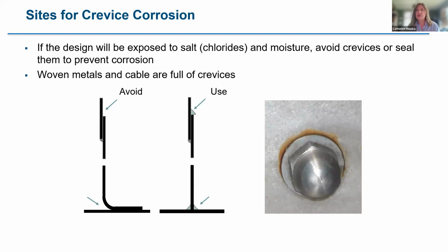This is an example of crevice corrosion under a bolt on a pavilion in Florida. It was type 316. It was the only area where there was corrosion. There wasn't any sealant under the bolt heads, and there was crevice corrosion. Wherever you have created a tight crevice where salts and moisture or pollutants can get into that crevice, you will likely have a place where crevice corrosion can occur. Sealing the crevices or avoiding them is ideal. If you're going to use a woven metal screen, like woven stainless steel, sunscreen, or similar, then you need to make sure that the alloy that you've specified has enough resistance to crevice corrosion so that you don't end up with crevice corrosion where every single line crosses.